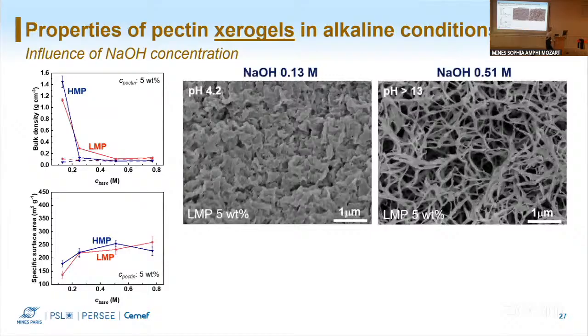What are the main reasons you think? What are the two effects that happen there? Why does a coarser structure allow ambient pressure drying? Okay, so from the capillary pressure equation, the Young-Laplace equation, we know that the capillary pressure is directly connected with the pore size. So the bigger the pores, the lower the capillary pressures.